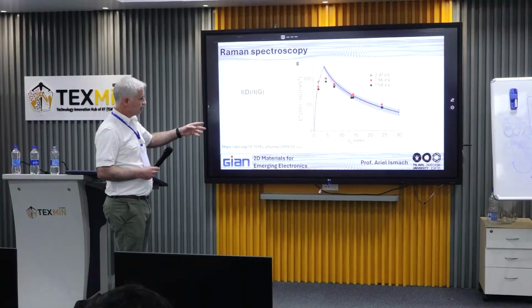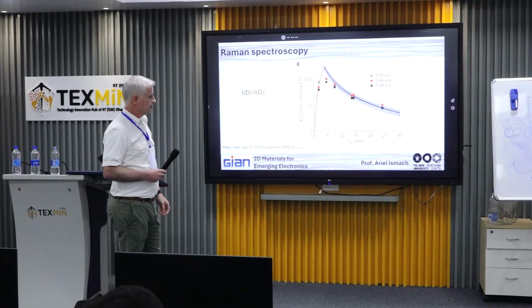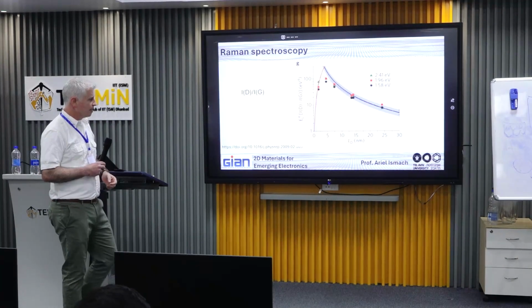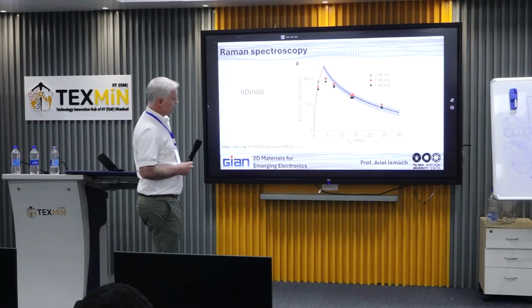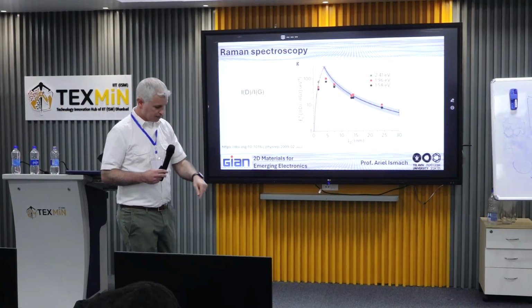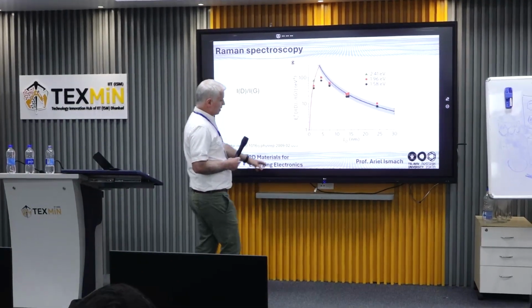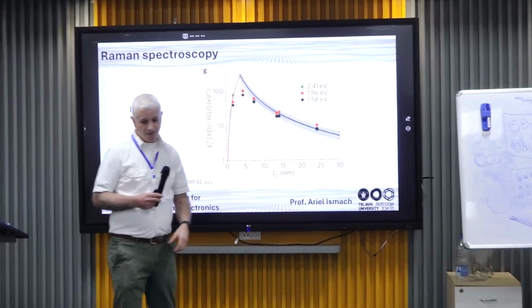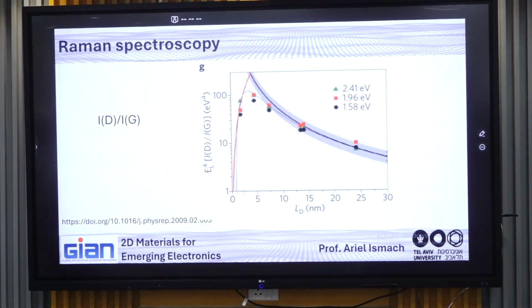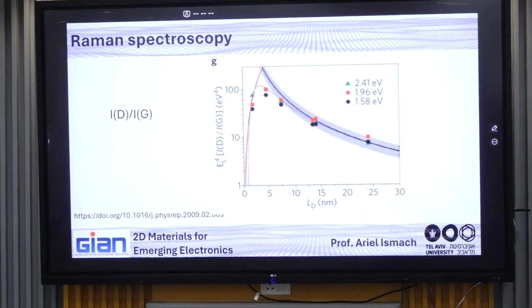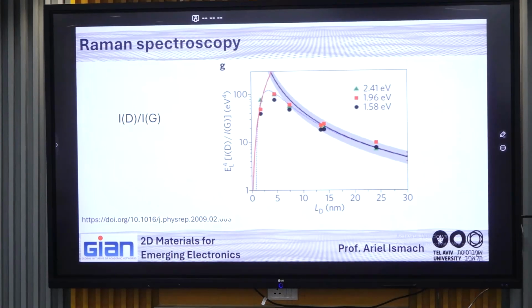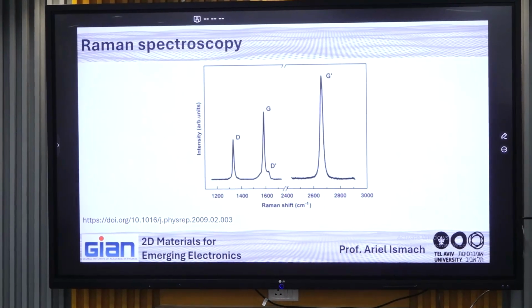And if you want to get deeper into the theory on that, it comes from work done 10 years ago by a group where they basically took a graphite and made defects by ion shooting, the ion beam. And then they measured the distance between the defects, and then they measured the different ratios. Very interesting theory. Anyway, this is the way to compare between the samples.